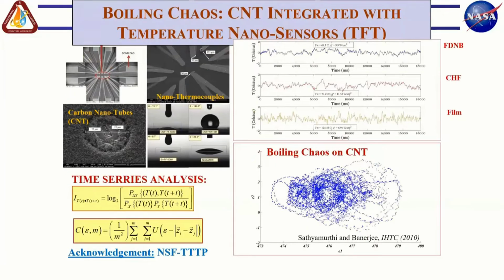Now these nanothermocouples, we could also use to look at the time temperature trace for different boiling regimes, like fully developed nucleate boiling, critical heat flux, as well as film boiling. And we saw that the chaos signature of these thermocouple plots, if you do it as a phase plot, the signatures of the chaos that comes out of these temperature plots actually changes depending on the boiling regime.